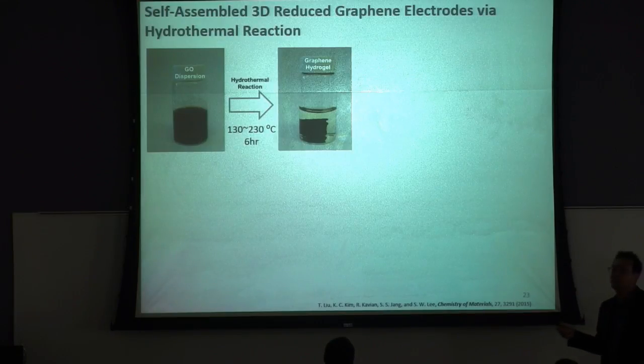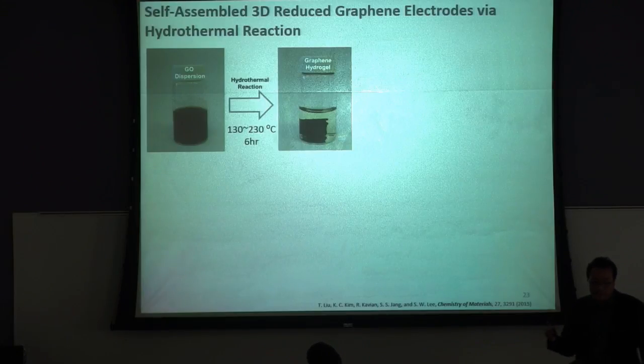So this is graphene oxide dispersion, right? Instead of the vacuum filtration process, we apply a hydrothermal reaction. Simply, we pour this graphene oxide dispersion into a closed vessel and heat this vessel to just over 100 Celsius. Then the water becomes a superheated phase, right? Basically, the water becomes superheated vapor, and it can generate a pressure.